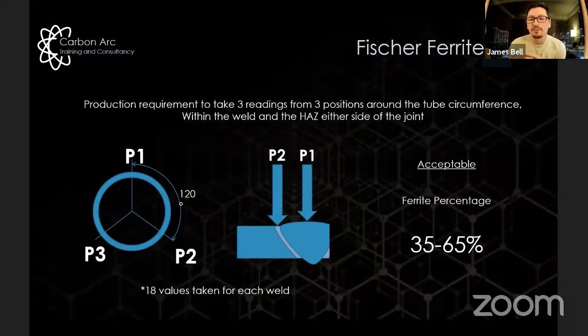For our project, we had to take readings from 3 locations around the OD of the tube. So this is position 1, 2, and 3 on the left, with at least 120 degrees between each position. And then we would take, say, from position 1, the 12 o'clock position there, 3 readings from the weld metal and 3 readings from the heat affected zone. And the average of those 3 readings needed to be between 35 to 65% ferrite, which is the normal acceptance criteria for welds in super duplex material.